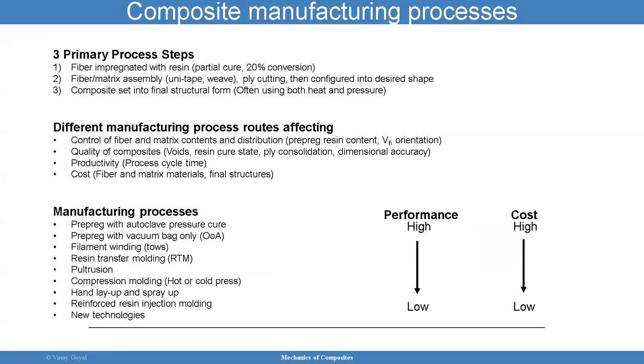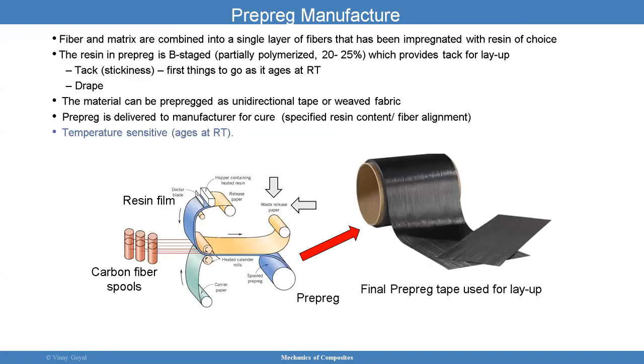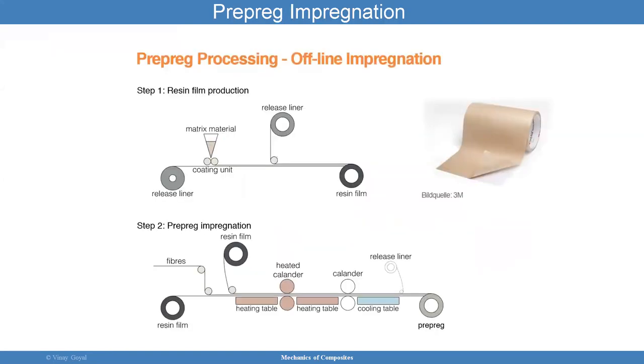And secondly, what I point out here is how the autoclave works. In essence, you're going to have some amount of resin flow, and the vacuum bag allows you to pull out all the potential voids between the lamina so that the polymers can cross-link from one layer to another. And so then the resin hardens, and you have a composite structure that has been formed.